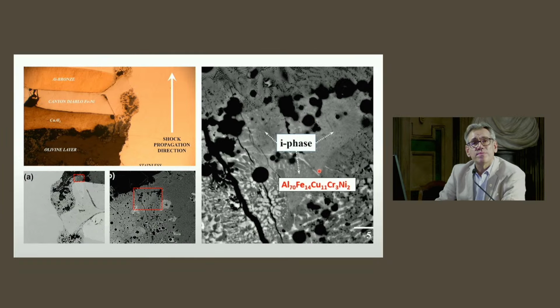With our surprise, at the very first shock, we produced an icosahedral phase with almost exactly the same composition as icosahedrite in terms of aluminum, copper, and iron - if you neglect the chromium and nickel components, which come from the stainless steel chamber. It was incredible.